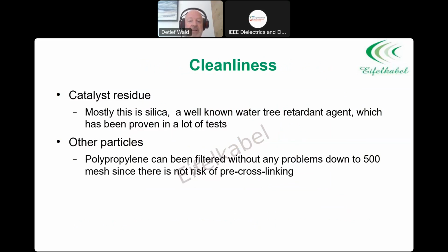The other thing is the cleanliness. One of the contaminations that you have in polypropylene, because it's produced via a catalyst, are catalyst residues, which is silica, and a couple of you might have heard about nanomaterials. The advantage of this is that the silicon or the silica is very well dispersed inside the polymer, and I think it's one of the best nanocomposites that you can have, and silica is actually known to be a water tree retardant additive. There are also other catalysts that are used, and I had a discussion a couple of weeks ago, and most of them have also been evaluated for HVDC applications.